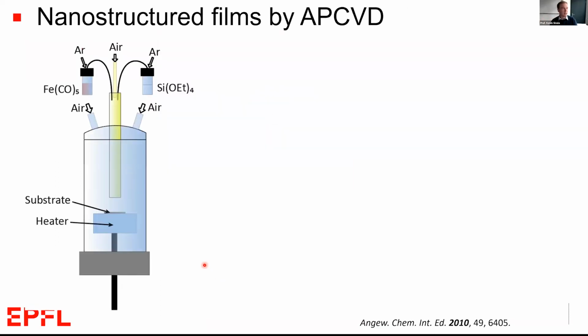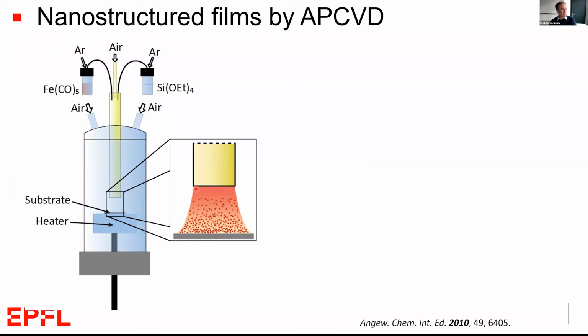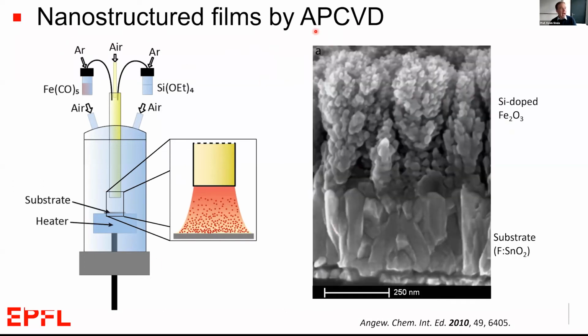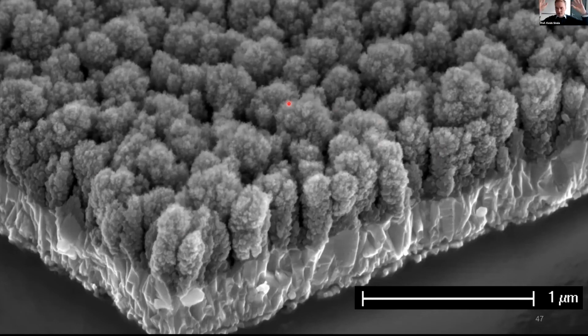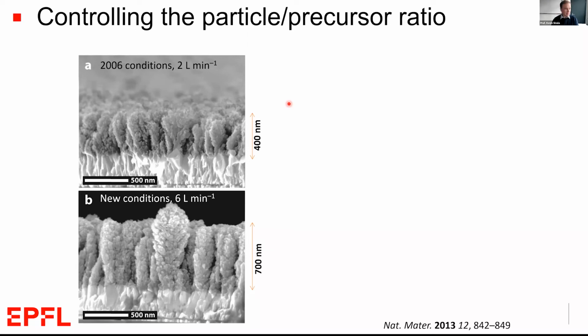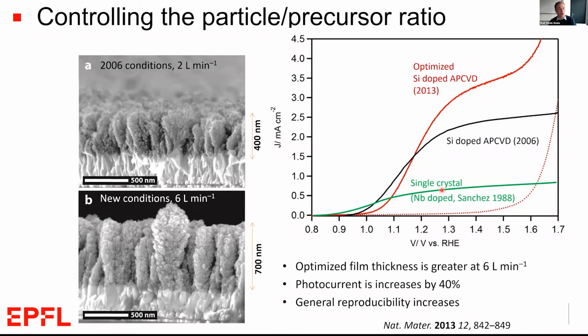And we spent a lot of time here at EPFL developing ways to nanostructure iron oxide. And here's one of the ways, using this atmospheric pressure chemical vapor deposition, that make these large area, high surface area nanostructures of iron oxide that can increase the performance. And we can see that here. The green curve is the photoanode LSV of a single crystal. And by increasing the surface area, by engineering the nanostructure, we can increase that photocurrent up to now about 3.5 milliamps per centimeter squared. But that's still a lot lower than the 12 that would represent a full quantum efficiency with this material.